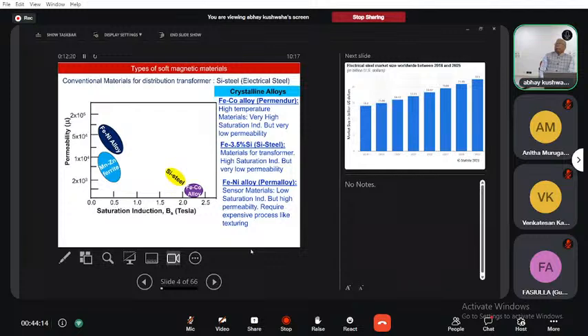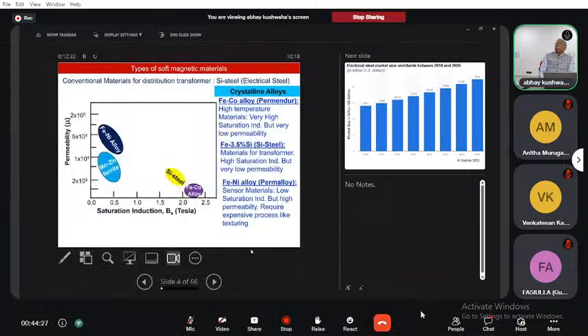You see, although we are talking about steel, if you see the true behavior of a steel, we require silicon as low as possible, and there should be a small percentage of carbon. But when we are talking about the silicon steel, our requirement is as much silicon as possible and as low carbon content as possible, because the carbon which goes into the interstitial site is very, very detrimental for the magnetic properties of a material.